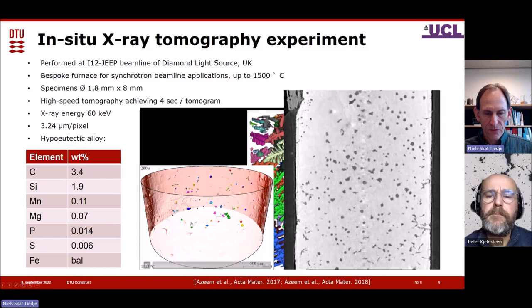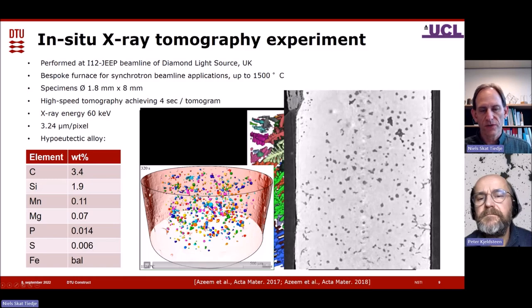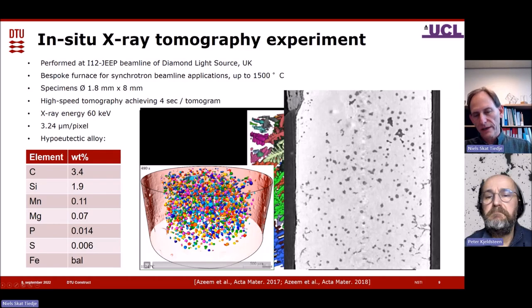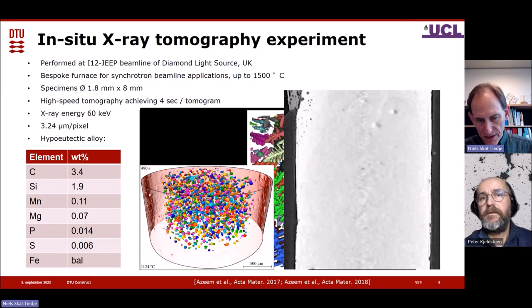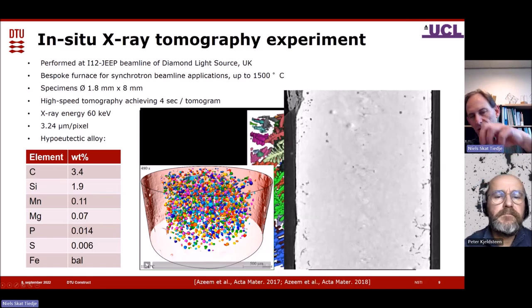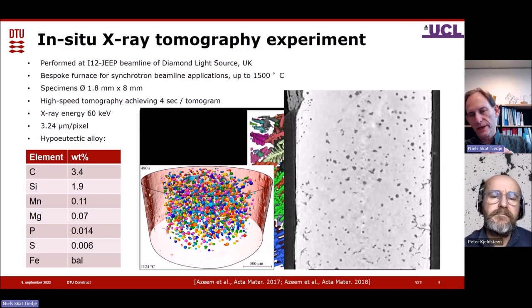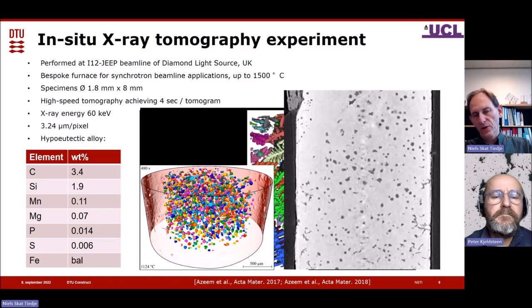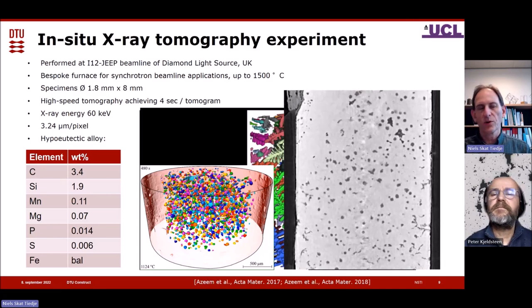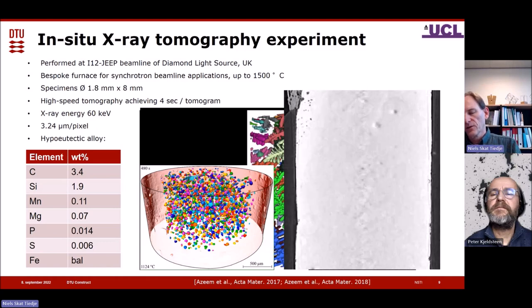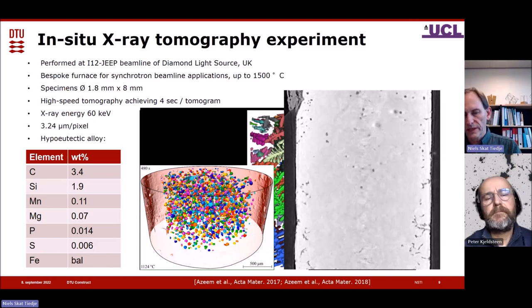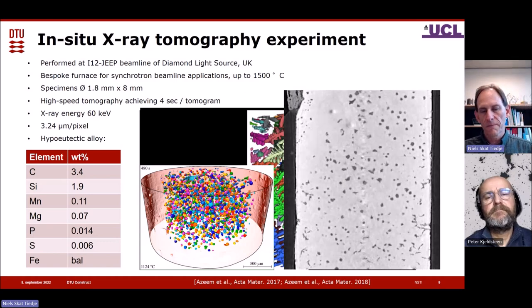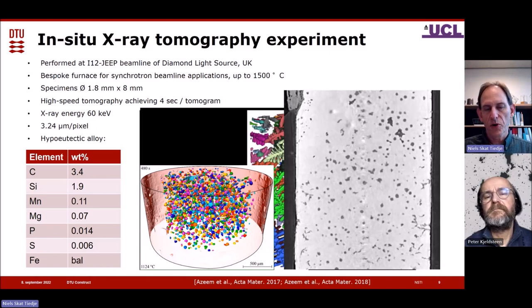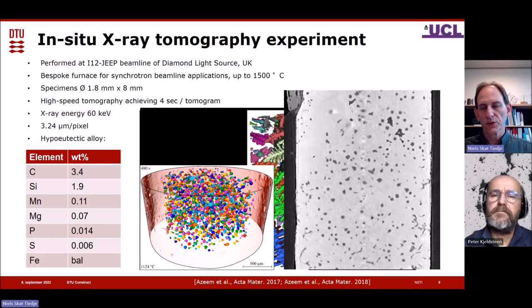You can see graphite forming at different time steps during solidification. And then you can go and isolate specific areas and say, let me look at, for instance, the center area, take all the particles there, look at them, at what time, what temperature do they form, how quickly do they grow, if they are not spherical, do they grow faster in some directions than others, and you can do a lot of analysis. So we did that, and then we also had some numerical models that predict solidification of ductile iron and held it against the results. And in the end, we did some modifications to those models to actually make them match what we see in practice.